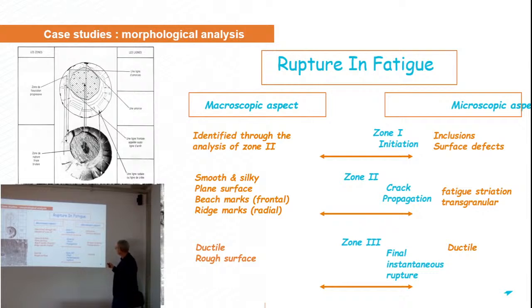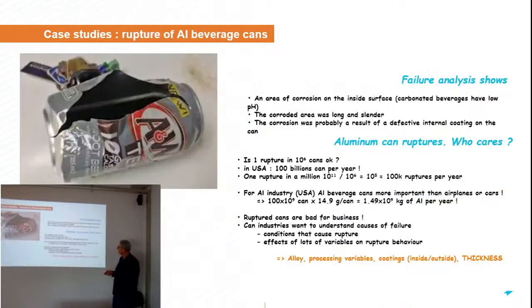And if you go to the first zone, probably with this microscopic approach, you can get some information about the initiation, either some metallurgical defect like an inclusion or a surface defect due to, for example, machining of the material. So, very interesting to analyze the fracture surface in fatigue. I give you here an example where you consider the fatigue of material or fracture mechanics of material.